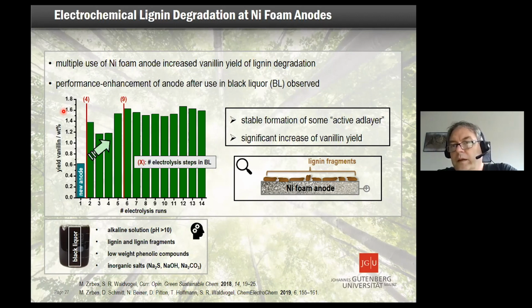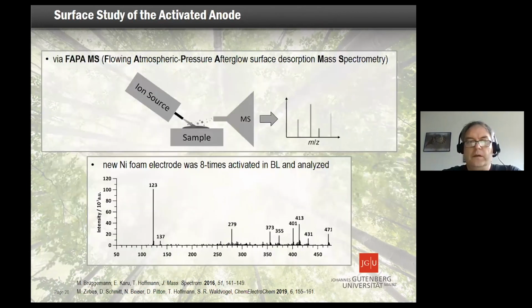And the question was, why is this the case? Why does it become better when you work it before in a dirty black liquor mixture? We were thinking maybe you have some lignin fragments on the surface which help in the conversion. It turned out you need an analytical system to work on that. Maybe there's some electrode fouling, and the way to do this at the time was FAPA MS, that means flowing atmospheric pressure afterglow. This generates some ions, and these ions operate like an APCI, and you do ionization, and the small molecules will be lifted up. And it turned out there's a molecule in there with a mass of 123.